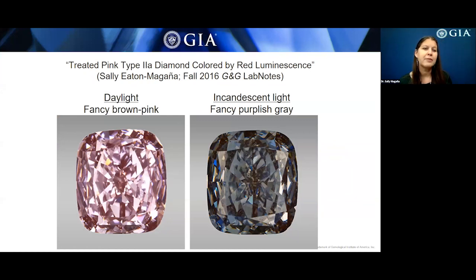Next up, I'm going to talk about this 4.2 carat type 2A color treated diamond. It was graded as fancy brown pink under daylight conditions and appeared as fancy purplish gray under incandescent lighting. The color change and this apparent alexandrite effect is due to strong reddish fluorescence of nitrogen vacancy centers under UV or blue light, and it's dominated by irradiation-related GR1 absorption under incandescent light. We identified it as a treated diamond that had been subjected to HPHT annealing, irradiation, and then subsequent low pressure annealing.